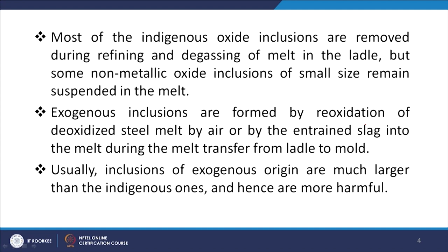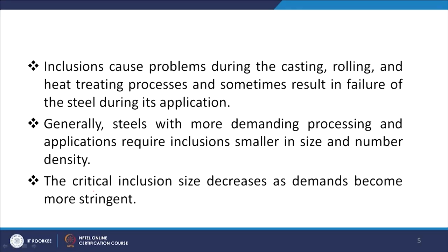Exogenous inclusions, formed because of reoxidation and slag entrainment, are normally much larger than indigenous ones and are very harmful. Larger inclusions are more harmful than smaller ones because they cause problems during casting, rolling, and heat-treating processes.